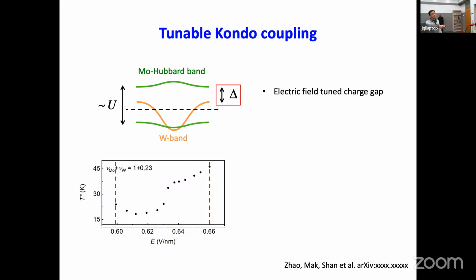And so you do get a minimum of the Kondo temperature, but not exactly in the middle. You can see asymmetry in the electric field dependence. In the simple model that people cook up, it's exactly symmetric. Touching the lower Hubbard band or the upper Hubbard band is exactly symmetric, but in experiment, it's not symmetric. And we believe that in experiment, the lower and upper Hubbard band in this system are not totally symmetric. So, yeah.